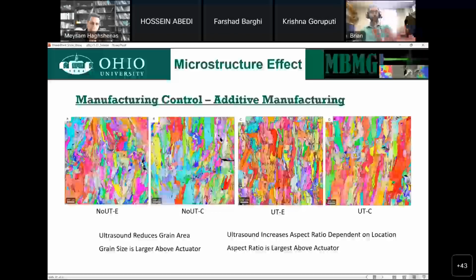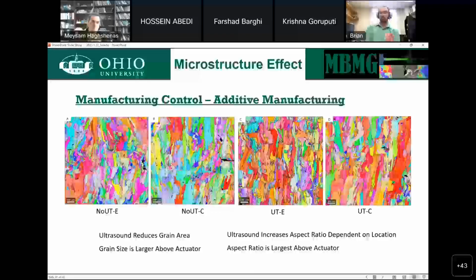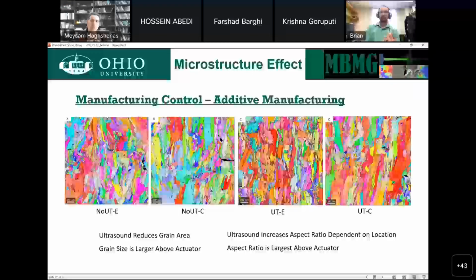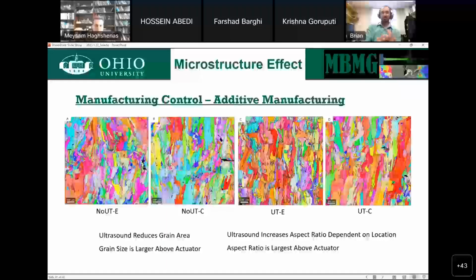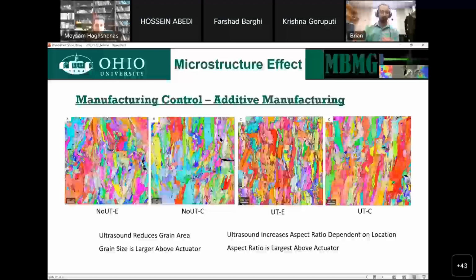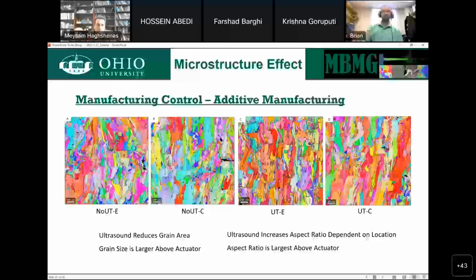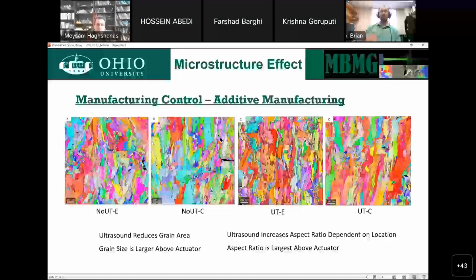The system that we used here, the transducer was about $100. It's the same kind of transducer that you have in an ultrasonic bath. You can put it onto this thing. The controller for it was about $50. Now, the controller we have is one frequency, one intensity. So if you're good with just one frequency, one intensity, then you could probably get away with putting a system like this in on the order of a few hundreds to a grand.